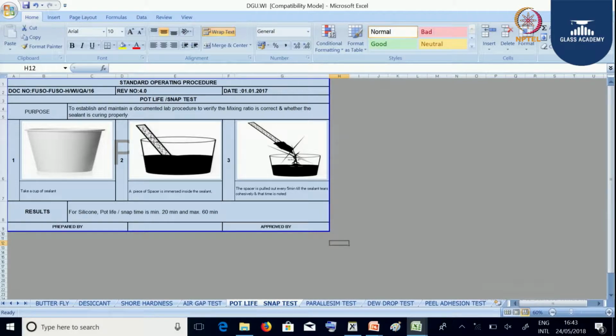The procedure we follow is: first we take a cup, and inside it we apply a sealant, then take a spacer and insert it inside the cup, and try to remove the spacer every 5 minutes. At a particular time it will not come out. We need to see whether it is a cohesive failure or adhesive failure, and at what time. If it is tearing within itself at a particular time, we need to note down that time. The result is, for silicone the snap time should be minimum 20 minutes and maximum 60 minutes. Basically the snap time determines the curing time between the glass and the spacer.